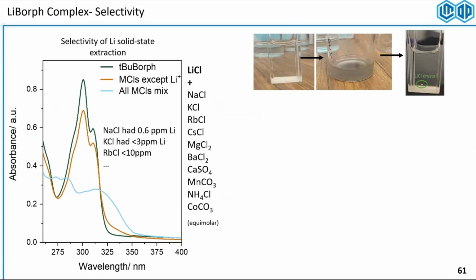So we sort of got greedy. I made a cocktail of many different salts without the presence of lithium and with presence of lithium. And we chose these to be sort of mimicking lithium battery waste, or the sea salt. And we were delighted to see that there's only a tiny, tiny shift when we add the cocktail without lithium. And as soon as the salt cocktail with lithium chloride, even though it's a salt, it's not dissolved in solvent or anything, we clearly see a big shift.